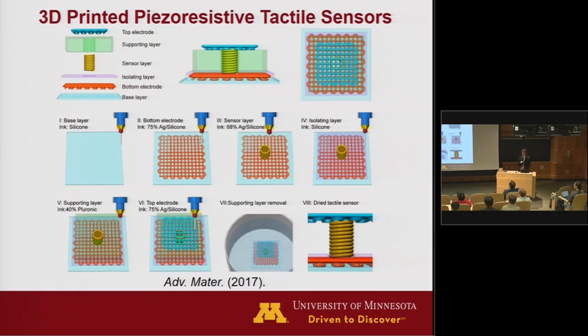In this case, this is a touch tactile sensor, which is piezoresistive. So we have a bottom electrode, a top electrode, and a coil that's printed here, which is touch sensitive. It's a formulation of nanoparticle inks within an elastomer matrix. It responds compressively to touch with a resistance change. And you can even do things like create sacrificial supporting layers here between the electrodes that can then be washed away in the end. So you have a freestanding eye-shaped geometry device here in the end. So very complex. We're now getting pretty sophisticated in terms of the types of printing we can do.